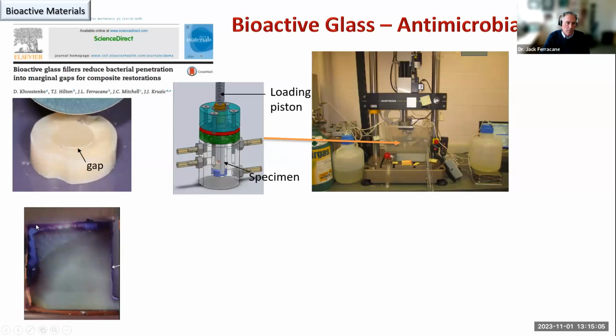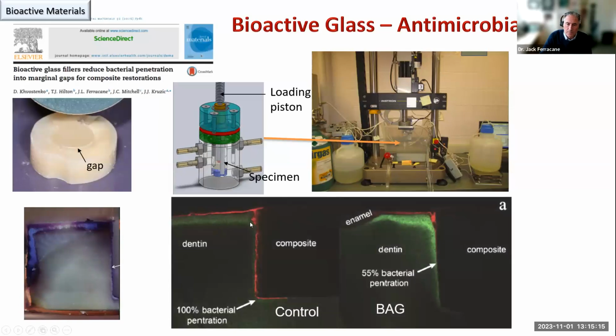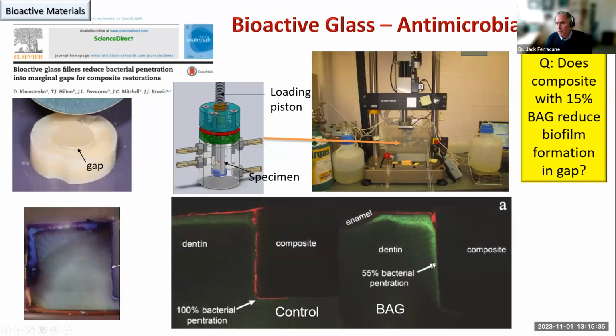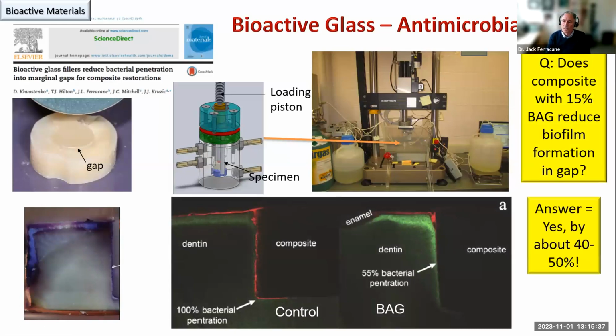And here's a section sample showing presence of the bacteria, in this case, all the way down the gap. This is dentin and enamel, and the composite was over here. And these are confocal images showing for the control composite, which did not have a glass, bacteria shown in red on the surface, penetrating down the gap and actually across the pulpal floor. Whereas when we had a composite that contained bioactive glass, we inhibited some of the progress of the bacteria down the gap. So does composite with 15% BAG reduce biofilm formation in the gap? The answer was yes, by about 40 to 50%.